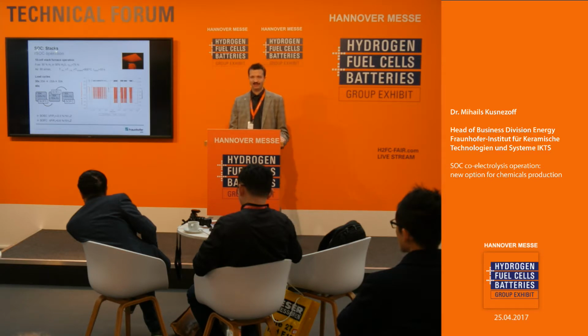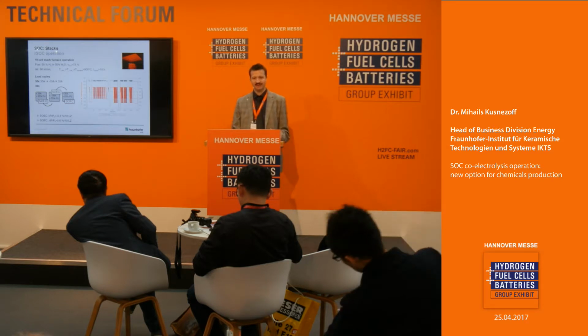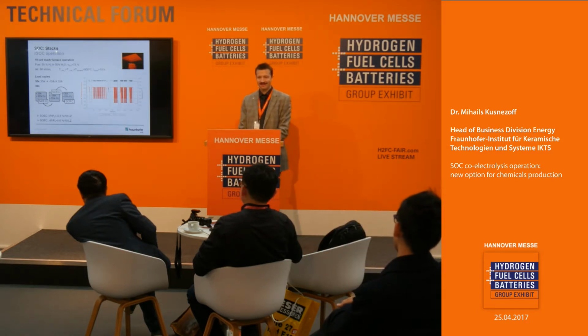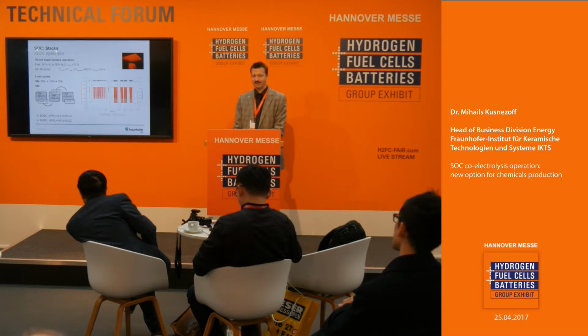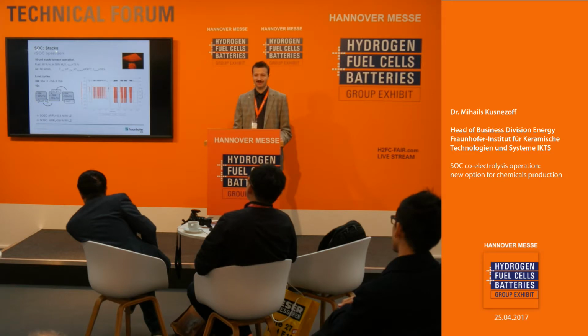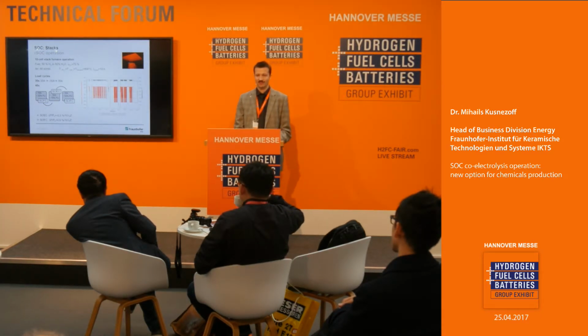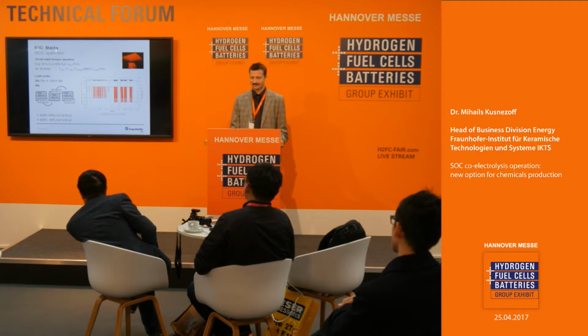We have also tried to switch between SOEC and SOFC mode, and we also have seen that in this case, even by operation at 800 degrees C, 12 hours in one mode and 12 hours in the other mode, we don't see a big degradation, because normally after SOEC operation, the changes we induce at low temperatures are reversible if we operate the cell in the SOFC mode.